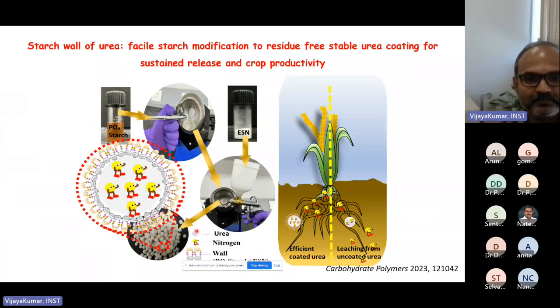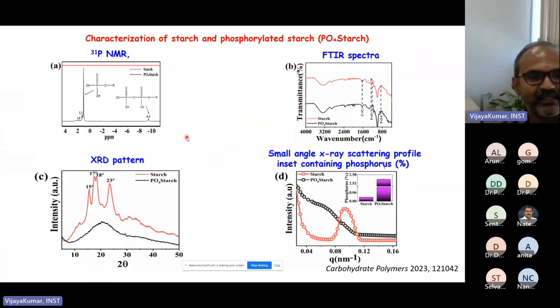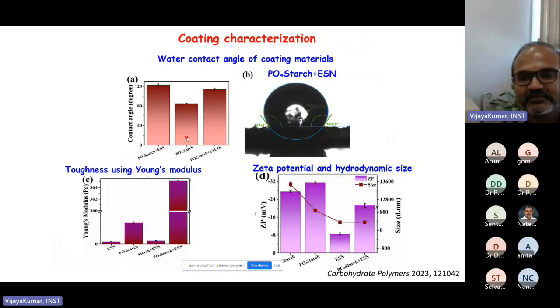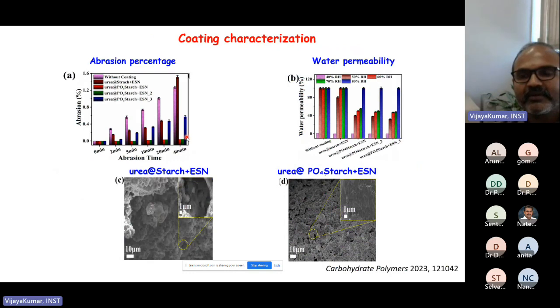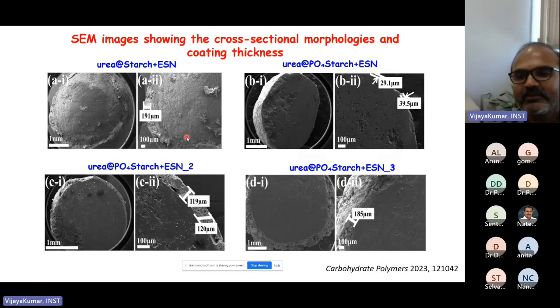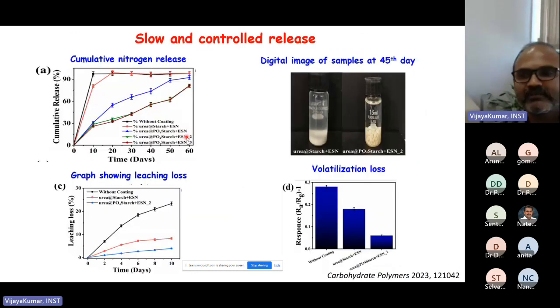So the same urea, uncoated urea, is taken, and phosphorylated starch is taken, and with the calcium source we are able to give a stable coating. And this is again the same characterization and the other things. For the want of time, let me skip all these things, which is just a repetition of the previous coating. And abrasion, permeability, everything has been checked, and with the change in the coating material we were able to change the thickness and cumulative release control.